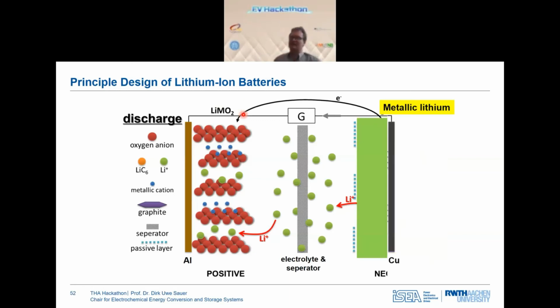And then there are many other things under development, but one is maybe also interesting because it targets getting rid of the carbon. Because what I haven't mentioned yet is that the carbon itself has 10 times more weight than the lithium, which is stored in the anode. So 9 out of 10 weight units in the anodes today are graphite. And the graphite is used only for safety reasons, but is not really increasing the energy density. The energy density is given only by the lithium.